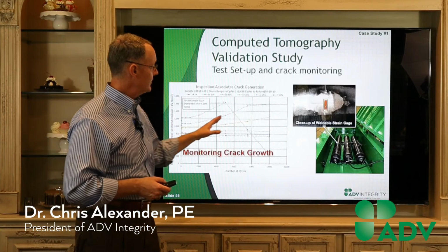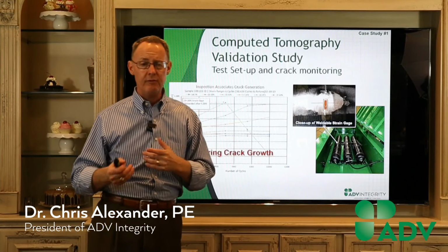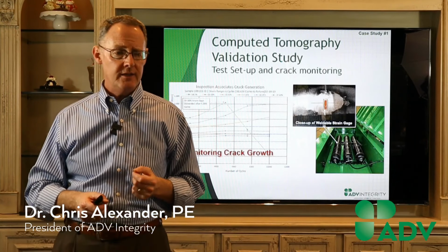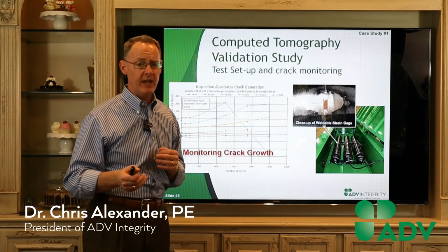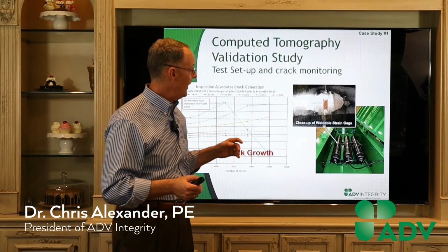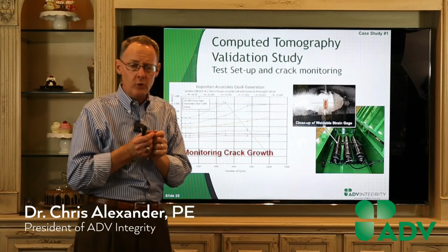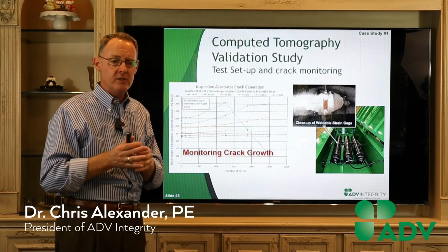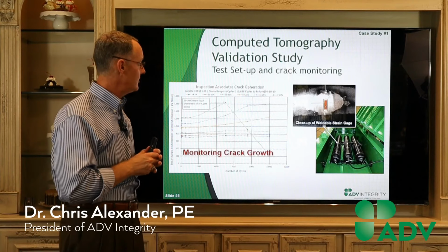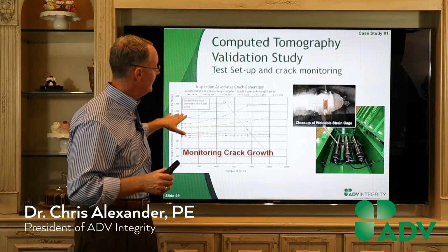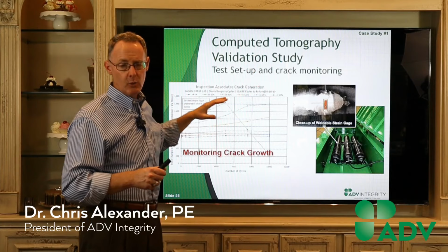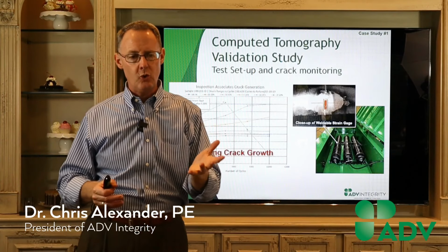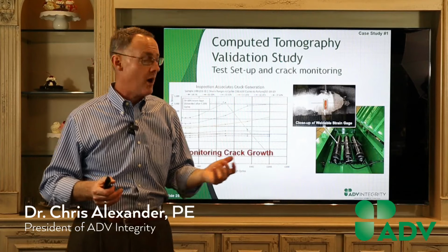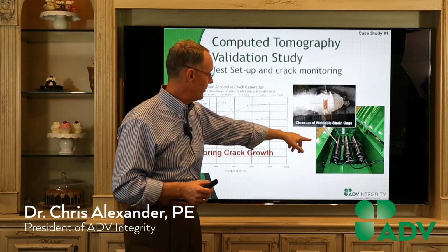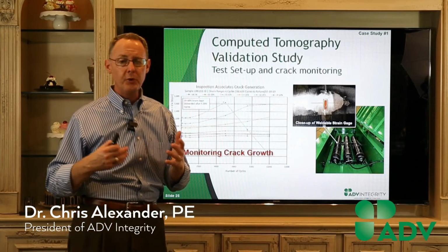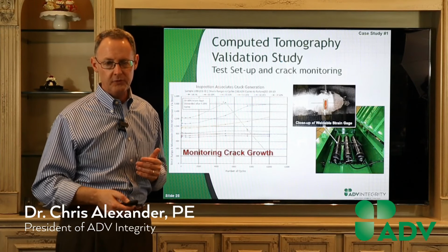And so as we're doing the cycling, we have a couple of different ways. We use clip gauges. DC potential drop is another technique that can be used. You can also use strain gauges. So what we're doing is we're looking at that notch as it opens up, as the compliance in the notch changes, and we start growing a crack, you see the strain really start growing. And so we've kind of developed some techniques that once it starts growing, then we stop the test and we know that we have a crack that's formed. And so here's the three samples in this program. We had multiple features in each of the pipe samples.